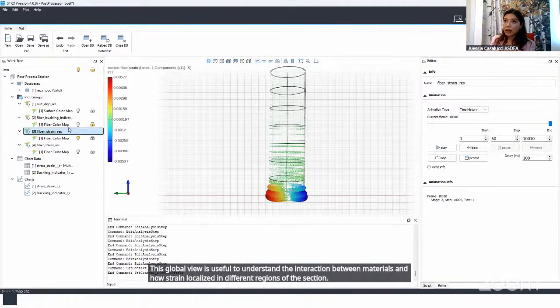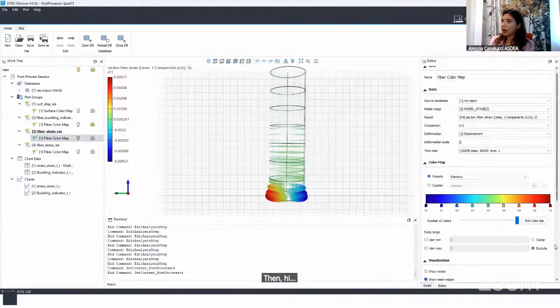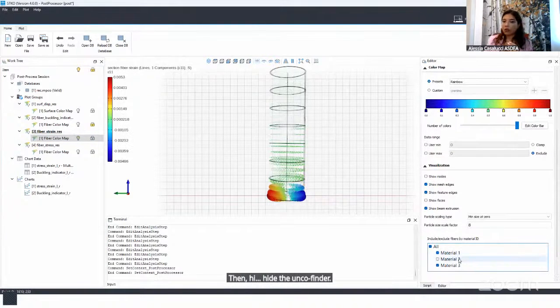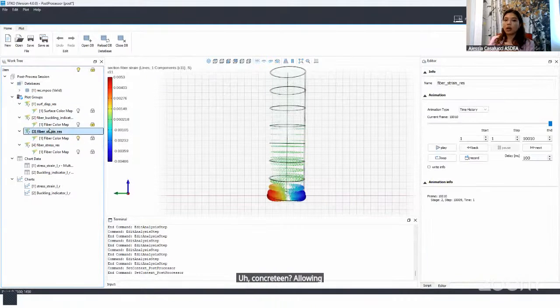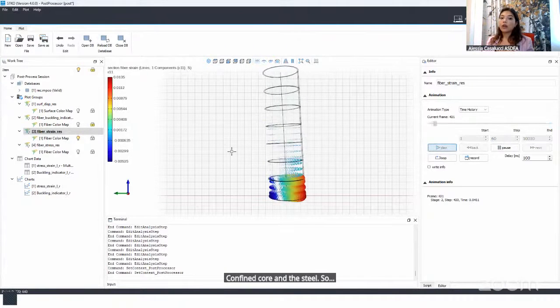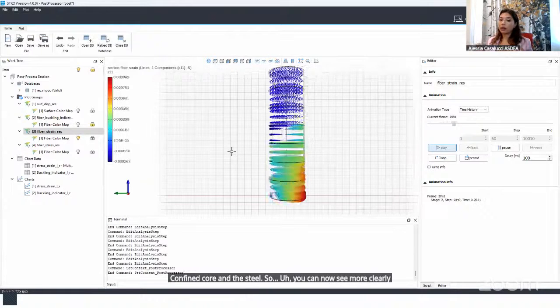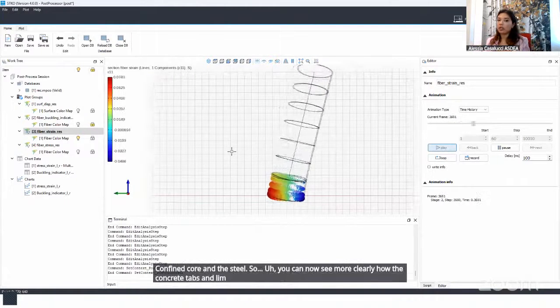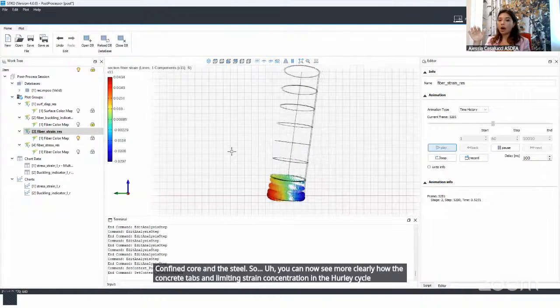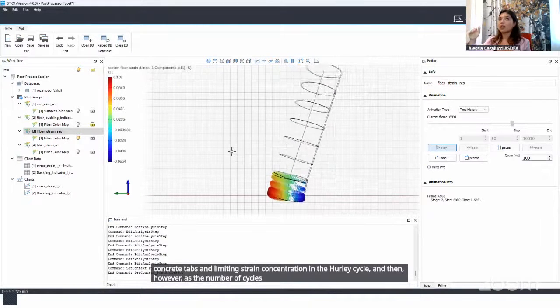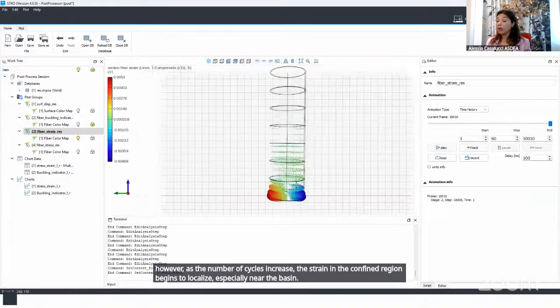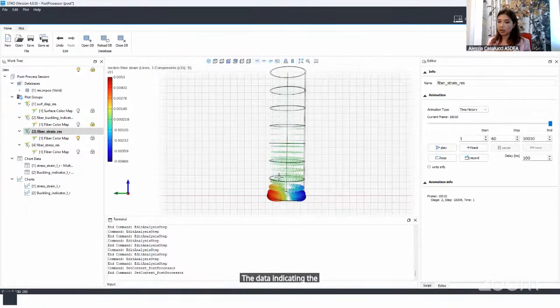This global view is useful to understand the interaction between materials and how strain localizes in different regions of the section. Then I hide the unconfined concrete, allowing us to better isolate and visualize the response of the confined core and the steel. You can now see more clearly how the confined core concrete helps in limiting strain concentration in the early cycles. However, as the number of cycles increases, the strain in the confined region begins to localize, especially near the base, indicating the formation of a plastic hinge.